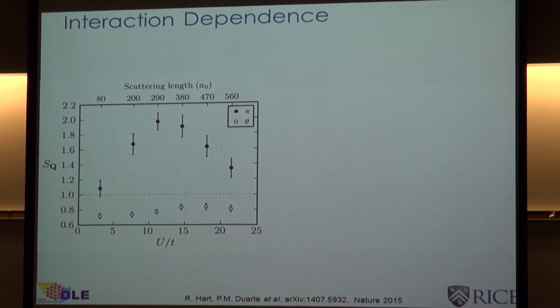All right, now as a function of interaction strength, so this is interaction strength on this axis, this is U over T, and this is the spin structure factor. You can see it peaks up at around 11 in our units, and then drops appropriately as you go away from that peak, very reminiscent of the Néel temperature that I showed you from the quantum Monte Carlo at the very beginning of the talk.